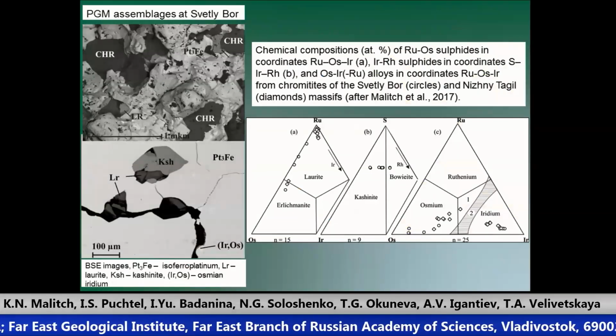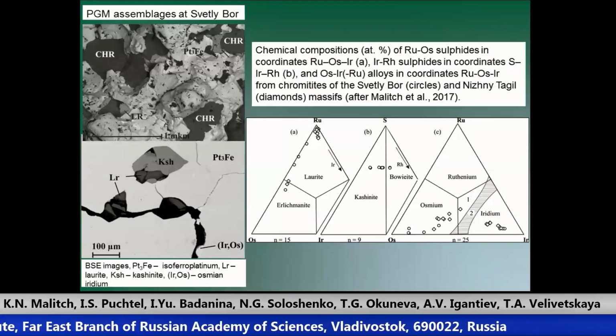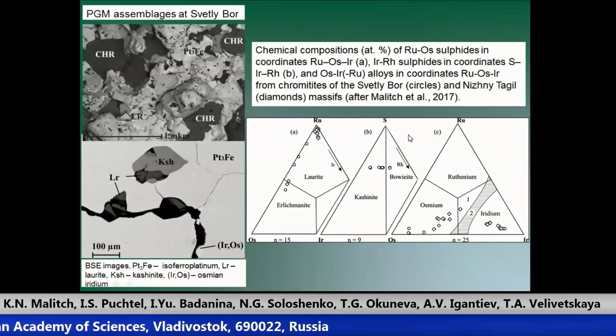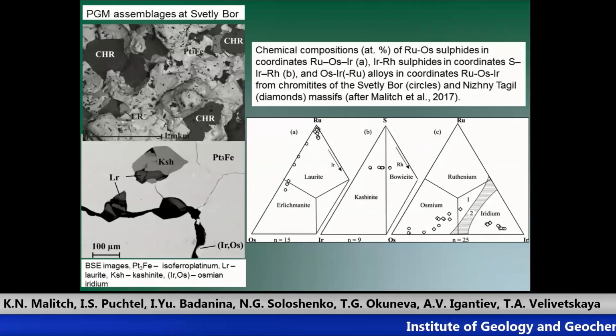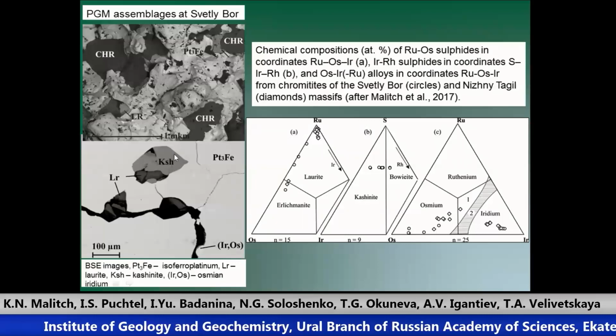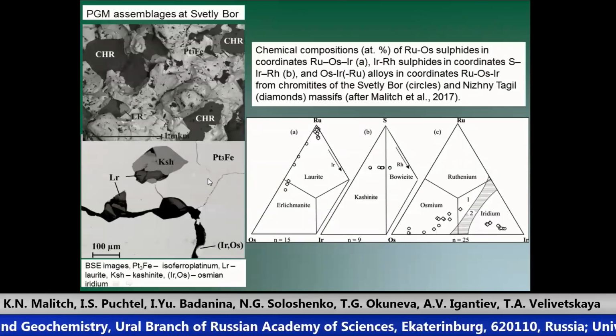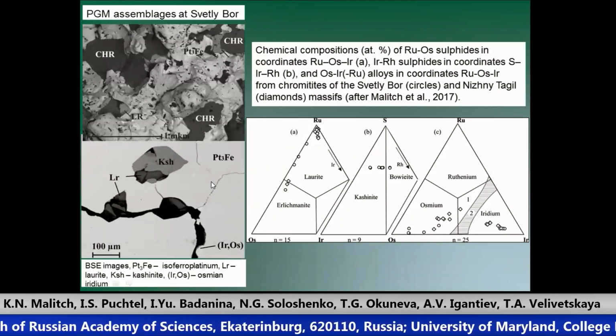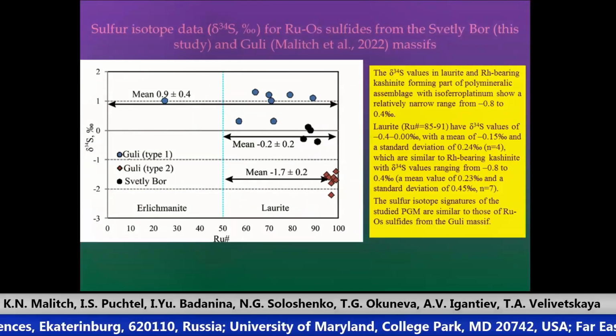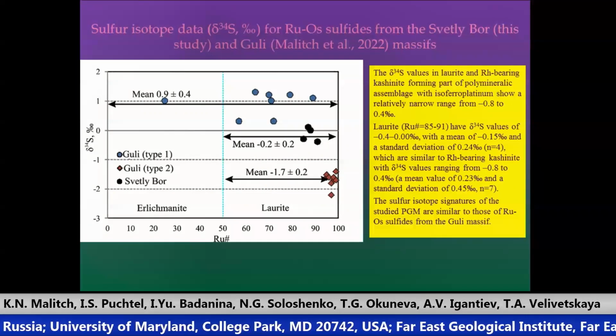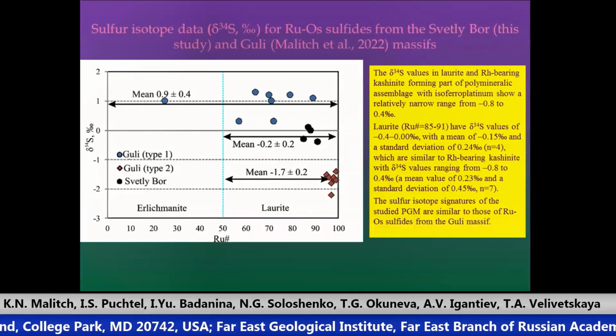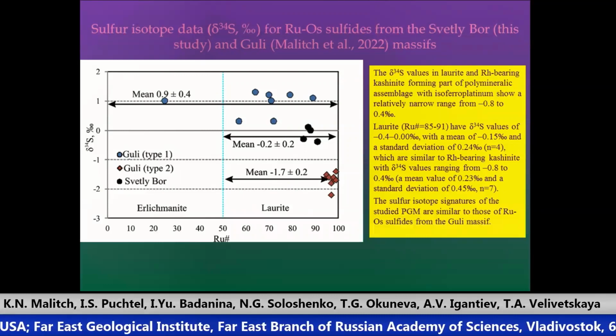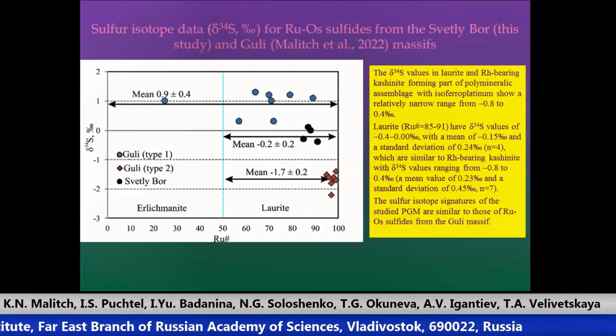Let us quickly have a look at chemistry of ruthenium-osmium sulfides, iridium-rhodium sulfides and osmium-iridium alloys from chromitites of the Svetly Bor, circles, and Nizhny Tagil, diamonds, from these massifs. So this is an example of PGM assemblage at Svetly Bor, in which we can see polyphase inclusions of kashinite and laurite, and monophase inclusions of osmium-iridium alloys in Pt-iron minerals. The δ34S values in laurite and rhodium-bearing kashinite, forming part of polymineralic assemblage with isoferroplatinum, show a relatively narrow range from minus 0.8 to 0.4 per mil.